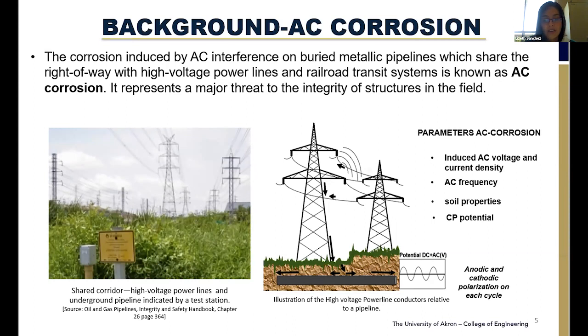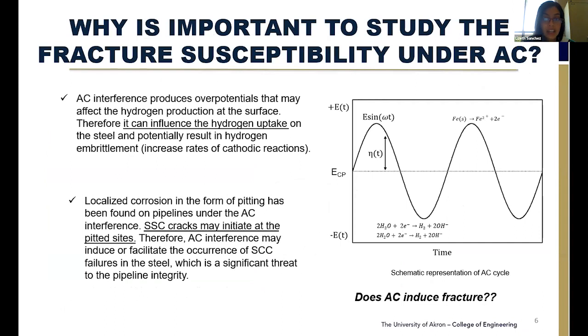Because of that, few studies have been done on AC corrosion, specifically on the effect on corrosion rate, but fewer on AC inducing cracking in the structure. So why is it important to study cracking susceptibility under AC? Well, first, because these overpotentials that we see here, especially the cathodic ones, produce hydrogen evolution and hydroxyl ions. But since we have AC, more AC voltage, more oscillation could produce more hydrogen, and this could increase the hydrogen uptake on the surface. If that happens, the hydrogen can diffuse through the steel and accumulate, producing embrittlement, the type of cracking that we know as hydrogen embrittlement.